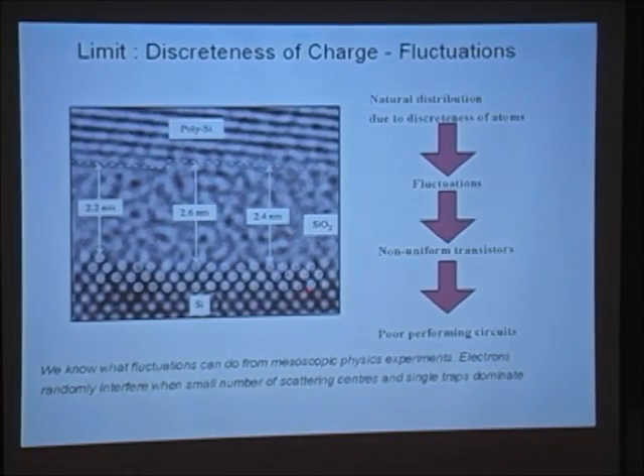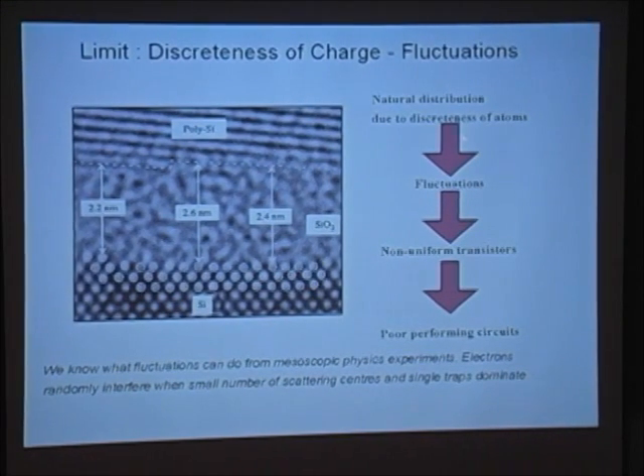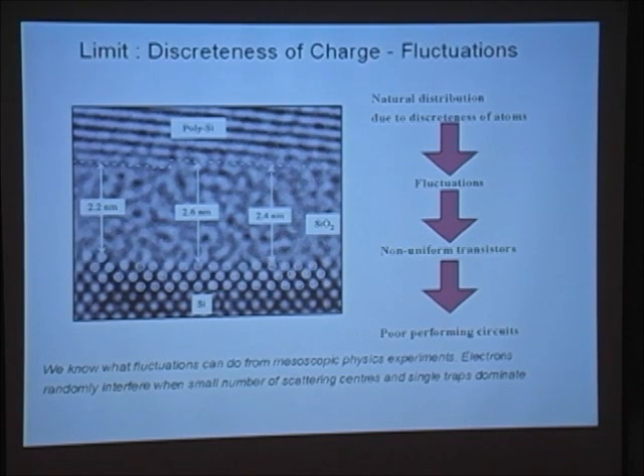Now, in terms of the science, what is one of the problems which one will experience? Well, here we just saw an electron micrograph of polysilicon as a gate, silicon dioxide and silicon, of a standard device. But there are fluctuations, and as devices get smaller, we can no longer average. One is accustomed to talking about semiconductors of 10 to the 15, 10 to the 16 dopants per centimeter cubed. But if you're down to a sample so small that even at this level of doping the total number of impurities is, say, 10, then their actual topology and distribution affects things. So you have to go beyond specifying average quantities. Indeed, average quantities don't tell you very much when you're that small.